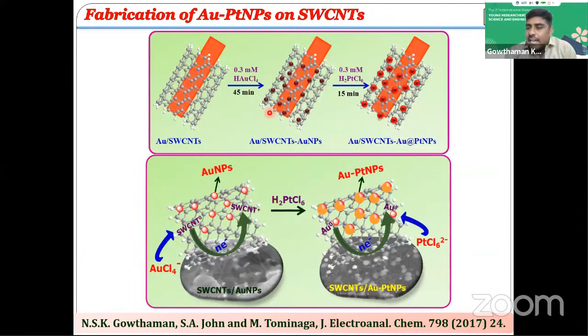Here we follow electroless deposition for gold and gold-platinum bimetallic nanoparticles. The carbon material is capable of reducing gold, so we just immerse the electrode into the solution containing chloroauric acid. Without any linker or reducing agent, gold nanoparticles were deposited on the CNT surface.